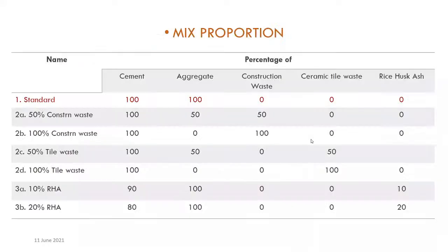See now, this is the methodology of study done in 3 different heads. First was for the standard specimen, where only cement and the normal coarse aggregate was mixed. Now here for the second one, 50% of the construction waste replacing the aggregate. Third, 100% of the construction waste, and then 50% of the tile waste, and then 100% of the tile waste replacing the normal aggregate. And the third part of the study was the replacement of 10% of the rice husk ash with cement and 20% of the rice husk ash with the cement.